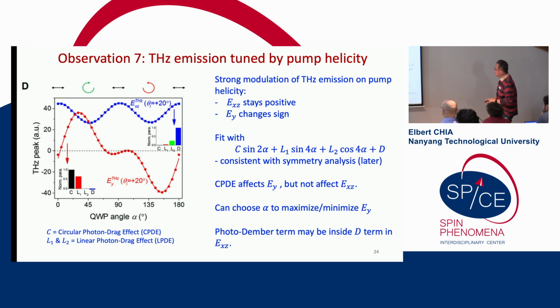What about pump helicity? If we were to use circularly polarized light instead of linearly polarized light, once again, the XZ component stays positive, and the Y component can go from a very large positive to a very large negative value. We fit it with this phenomenological model, and we found that the circularly polarized light affects EY a lot, but doesn't really affect EXZ. And so once again, we can choose alpha to maximize or minimize the Y component of the emitted terahertz pulse.